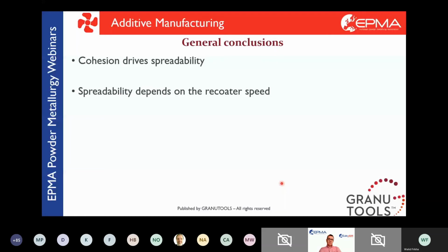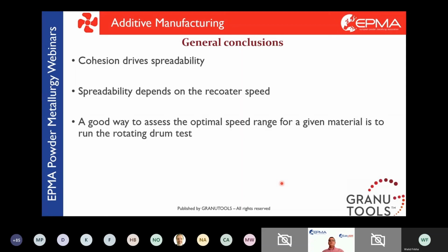Spreadability depends on the recoater speed. Depending on the speed you choose, you will not spread in the same way. Some powders have shear thinning behavior, some have shear thickening behavior, and you can assess that with the rotating drum test. A good way to assess the optimal speed range for a given material is to run the rotating drum test.